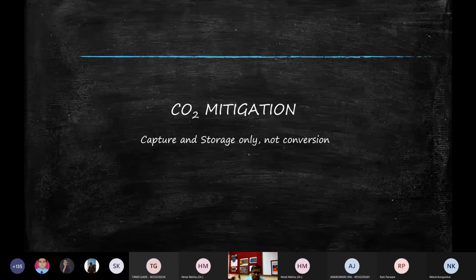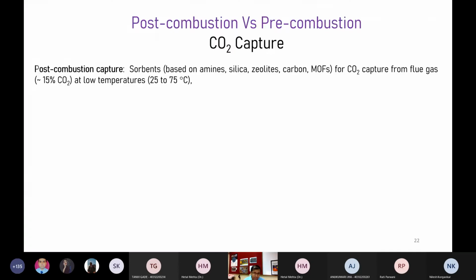So now how do I use this for CO2 mitigation? Only capture and storage, not the conversion. There are two ways to capture the CO2. One is you capture the CO2 from the flue gas that is coming from the chimney, which is say around 15% CO2, with a temperature that can be brought down up to 75 degrees Celsius.